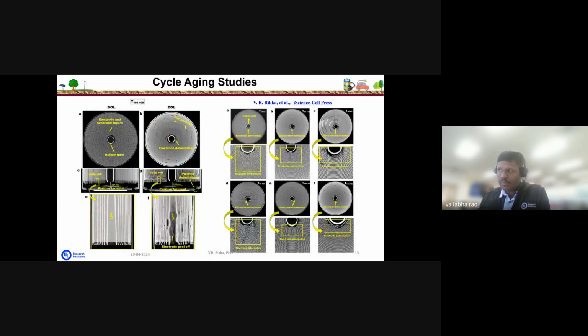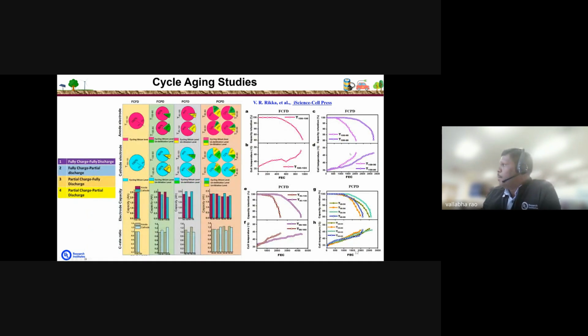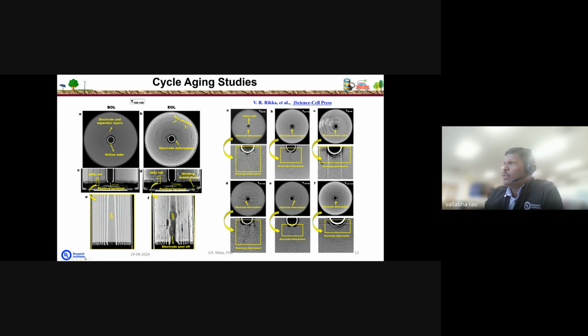And then to understand the main aging mechanisms involved in these test conditions, we performed non-destructive characterization using X-ray tomography analysis. So this is the beginning of life, an uncycled lithium-ion cell. And when we carried out the cycle life at different test conditions, for example, at the end of life for the full charge, full discharge condition, we can see the electrode jelly roll is completely deformed, and there are many gaps. These gaps we can call gas pockets, and these gas pockets were formed due to electrolyte evaporation over the cycles.